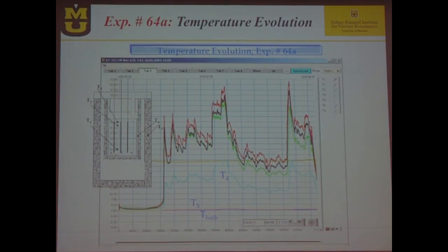These are the temperature distribution of the same experiment. You see that there is a full correlation with all the independent temperature elements. The power is extracted from T4 and T5, but these are for indication, and all of them are in full agreement. Even the vessel, which is a 40-liter vessel, was elevated in its temperature due to the burst of heat which was released from the cell.